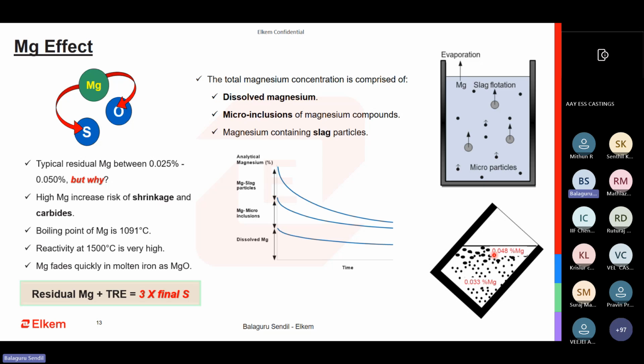You are prone to shrinkages, you are prone to carbides. At the same time, when you're using a very low magnesium FSM, 6% or 4-5% magnesium, and you have a residual Mg of 0.030 and you get excellent microstructure, then we need to understand that what we are measuring is not an actual representation. The magnesium level is much lower, but if you can ensure that whatever magnesium you are measuring is mostly in this micro inclusion category, then you get the best result.